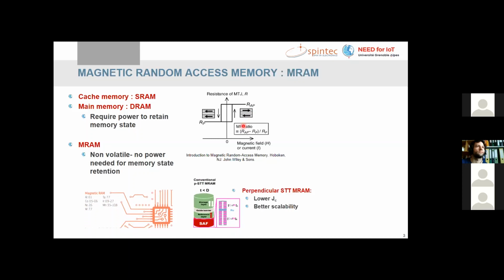As I was saying, in this European Commission study from last year, they did not identify platinum as contained in this MRAM, because they were addressing a type of MRAM that was used several years ago, with an aluminum oxide barrier and an in-plane magnetized configuration. But nowadays it is more common to use perpendicular STT-MRAM because it has lower current requirements and also better scalability to lower nodes.